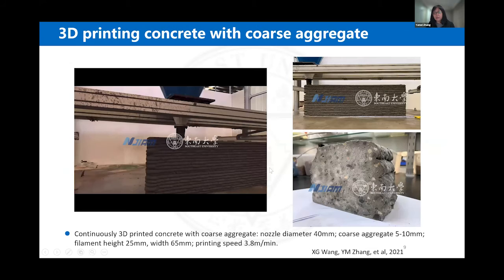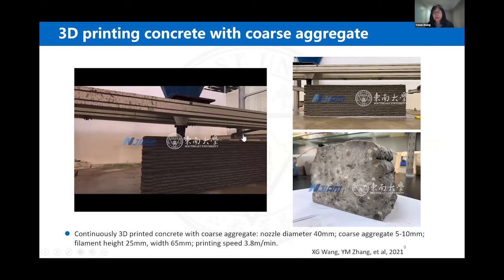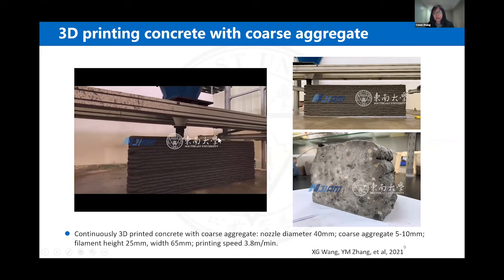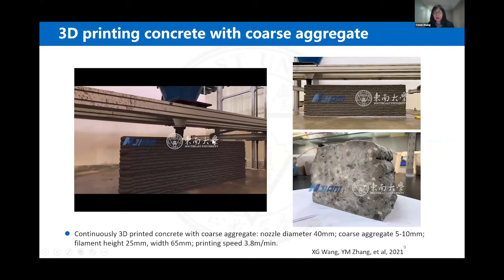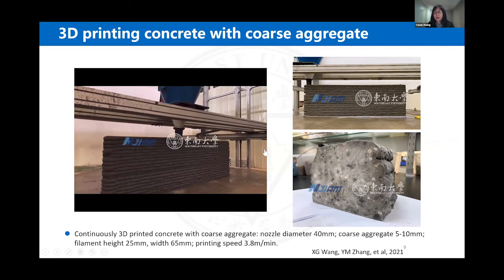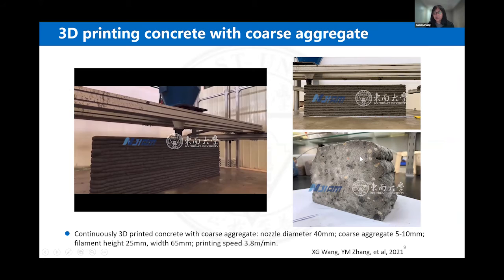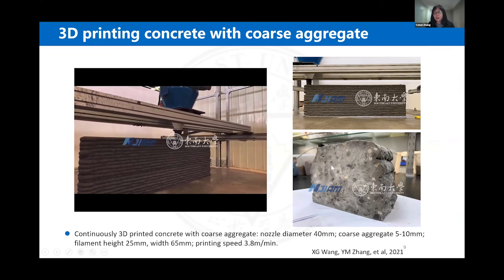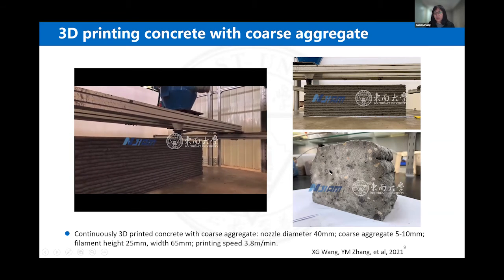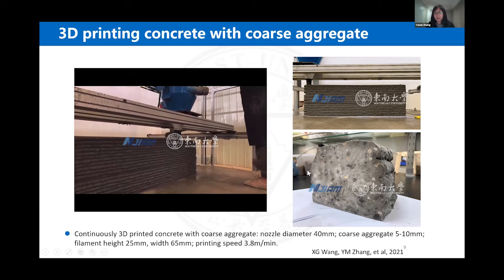So in our lab, we have developed some technology to print with concrete with some coarse aggregates. Here you can see we can smoothly print the concrete with coarse aggregate, and you can see there is no interface problem for this concrete.